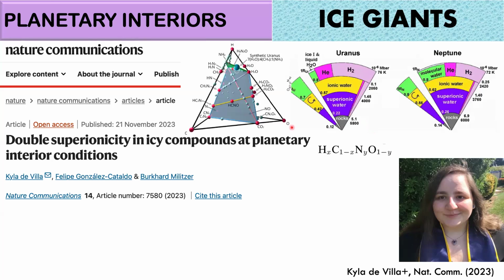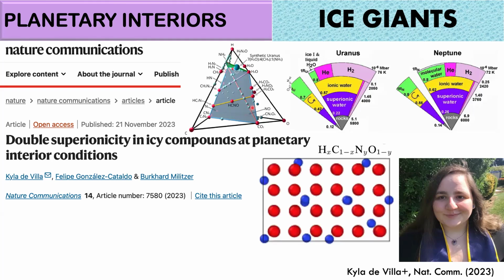So in the quaternary diagram of different formations of phases, you can find new materials like HCNO, a completely new solid. And what Kyla did was analyze basically 10 of these materials and expose them to different pressures and temperatures to see what would happen with them. And what she observed is that not only did the superionic phase appear, where the hydrogens are flowing like a liquid, but a second species, in this case nitrogen, was also flowing like a liquid in the lattice of still stable oxygen atoms. So this was a new phase of matter that had never been reported before, and that's why it made it into Nature Communications.